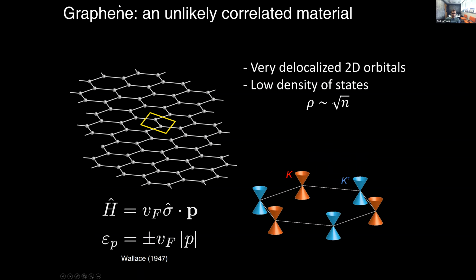So at a glance, graphene is a very unlikely correlated material because basically its density of states is very low. In monolayer graphene, you have very delocalized two-dimensional orbitals, and as a result, they have a very low density of states. Their density of states actually goes like the square root of the density, detuned from the Dirac crossings that you get at the corners of the Brillouin zone.